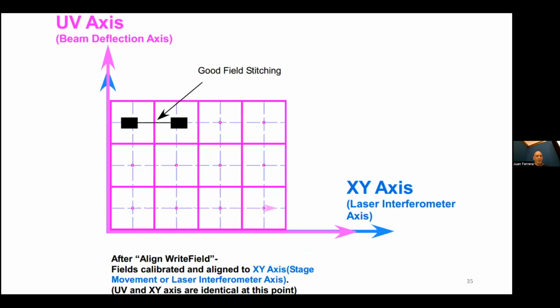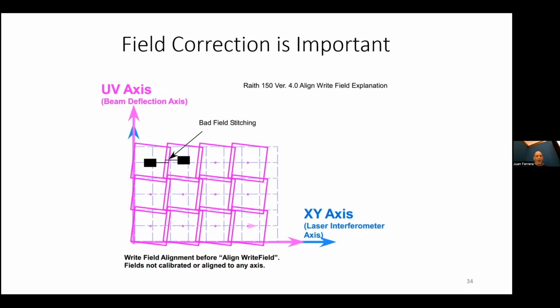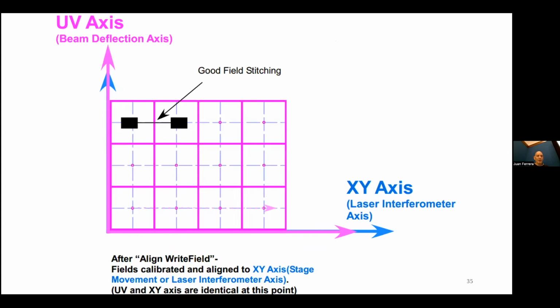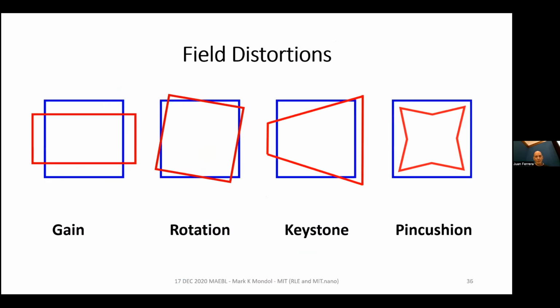Before we calibrate the beam, you have two features that are supposed to match right at the edges of the field, and they don't. After we do calibration, everything lines up so that our beam is moving along the same axis as the XY interferometer is, and features that cross field boundaries will butt up against each other perfectly, or as best we can. So here are examples of field distortions, and of course, you don't just get one distortion at a time, you get a convolution of more than one kind of distortion at a time.